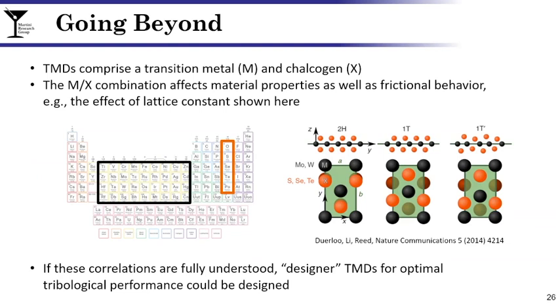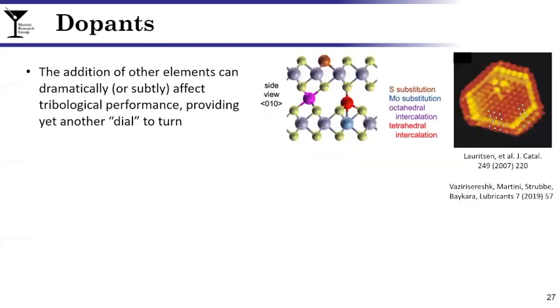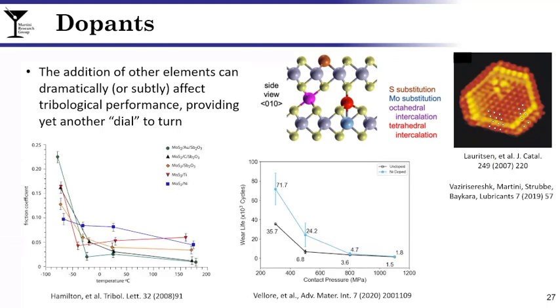And if we can understand how the energetics and the lattice spacing affects friction at the fundamental scale, we can, again, kind of slowly turn this knob to achieve the friction behavior that we wish to have. Another knob dial that one might turn is the use of dopants. And the term here, dopants, refers to the addition of relatively low concentrations of other elements. These other elements may appear within the MoS2 crystallographic lattice. Shown here is a schematic where we see 4 different possible locations for a dopant, or they can appear as different phases. Regardless, the use of dopants has been found to dramatically affect tribological behavior.